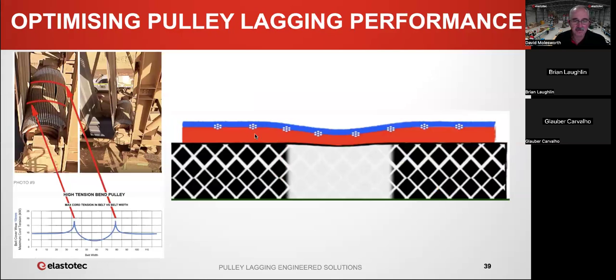This is a result of, this picture here, a pulley that's operating in contact with the dirty side of the belt. So it's operating with a worn belt profile. That worn belt profile creates localized shear forces. This is a graph across the belt width and measuring the minimum chord tensions inside the belt. So you get these peaks at the edge of the wear profile, and it's this cyclic localized shear that with cold bond lagging can cause this sort of separation and failure.